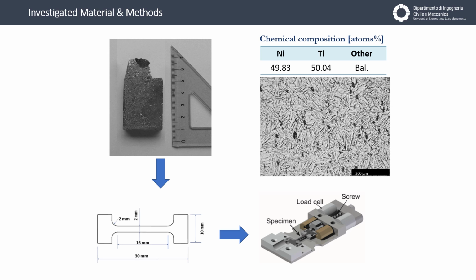This specimen has been put in a tool. It's a mini machine, a patented mini machine, which allows us to perform a loading test using a load cell in order to measure the total force applied on the specimen, and with an LVDT we can control the movement of the crosshead. This tool is able to put under load the specimen inside of a machine able to perform the XRD test in order to observe the diffraction spectrum, which is the base to better understand the position of atoms, and in this case the structure, the microstructure.